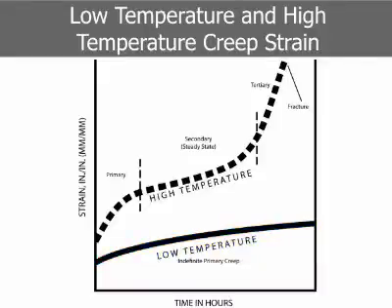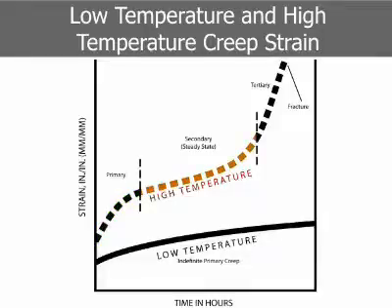At higher temperatures, primary creep — which is the shortest phase in terms of time — begins at a relatively fast, diminishing rate. The point at which the rate becomes constant is considered the end of the primary and the beginning of the secondary phase. Secondary creep, the longest phase, progresses at a constant rate.